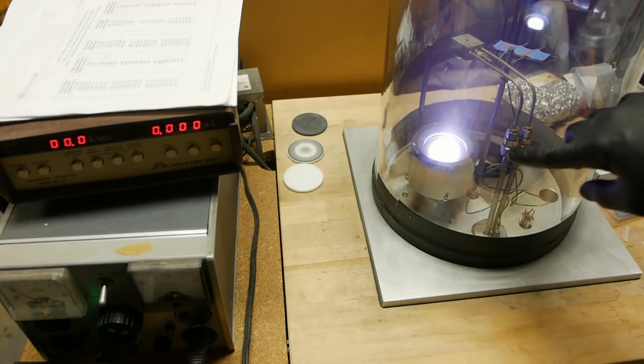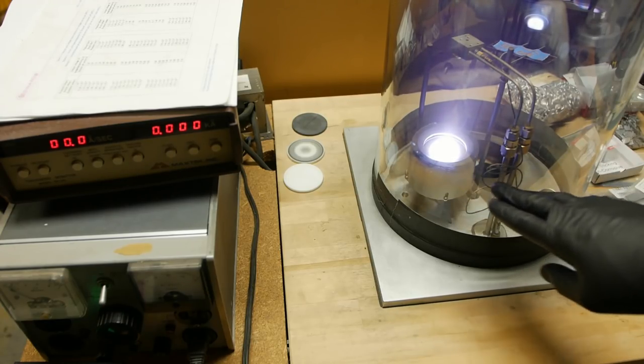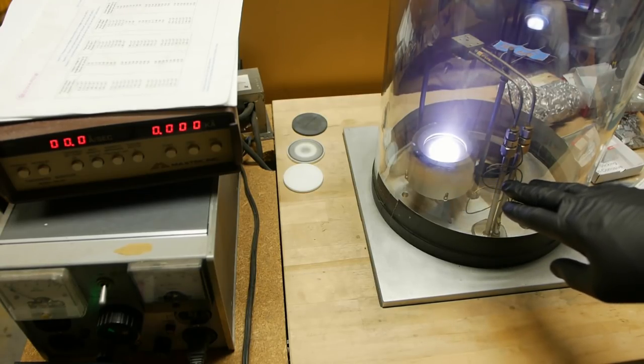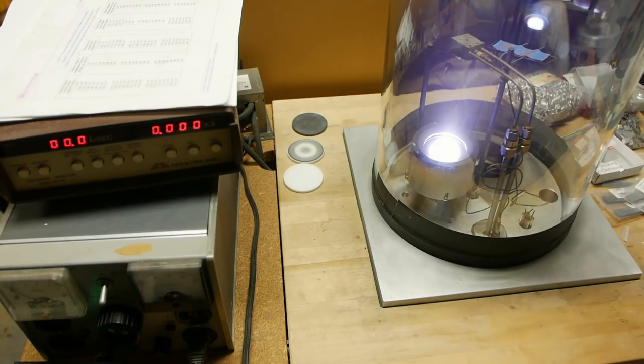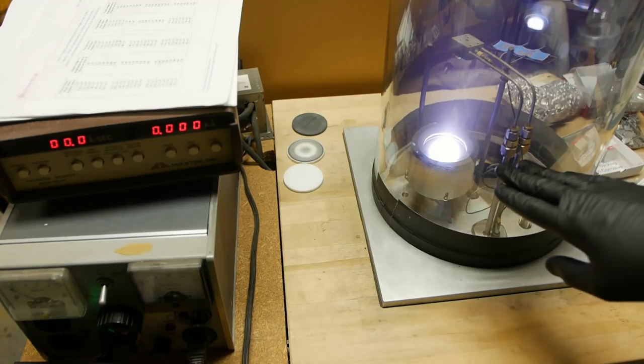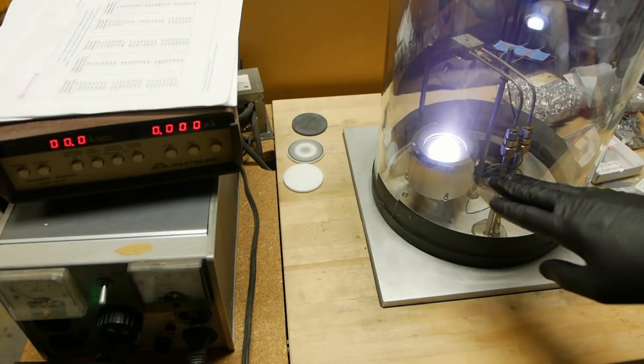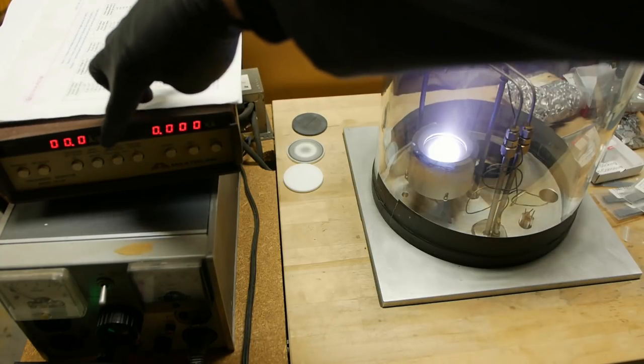And it's purplish color now because there's a piece of titanium. We're going to sputter titanium. But in air, this bell jar was open and the titanium was exposed to the room air, which means it's got titanium oxide on the top. And as you can see here, we're not sputtering anything yet. We've got all zeros across the board. And that's because the titanium oxide is very difficult to sputter.